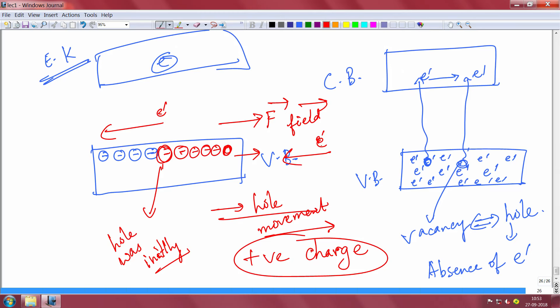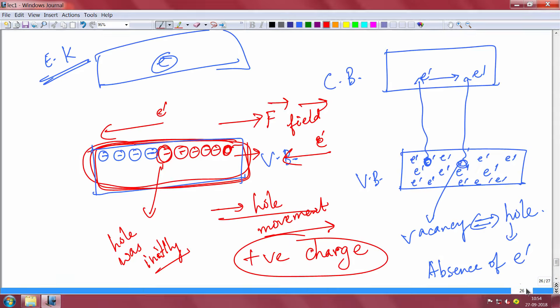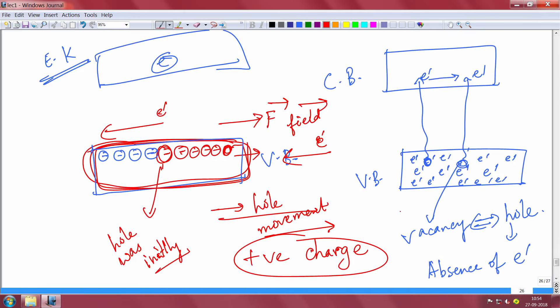If everything was packed with no hole, all electrons are there and cannot move — total momentum is zero. But now with a hole, the total momentum is not zero. The hole momentum is essentially the negative of the total electron momentum. The hole is the opposite of the electron, but its mass is not the same as an electron.